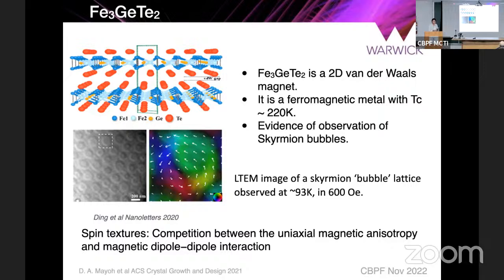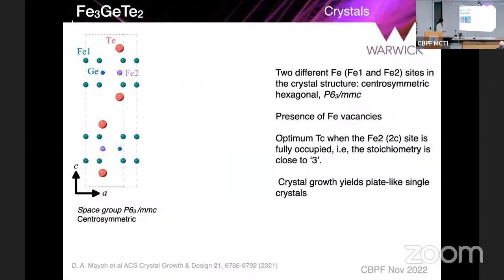There are a lot of theories proposing what might lead to the formation of the skyrmions, and one proposed in this material is that there is a competition between the uniaxial magnetic anisotropy and the magnetic dipole-dipole interaction. So there's a lot of debate about how these are stabilized. So let's look at this structure again.